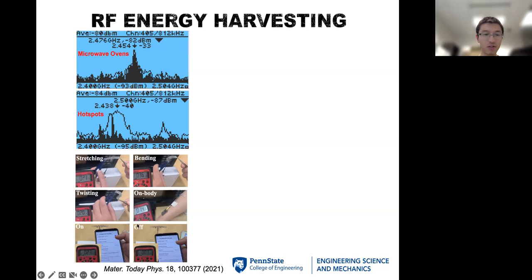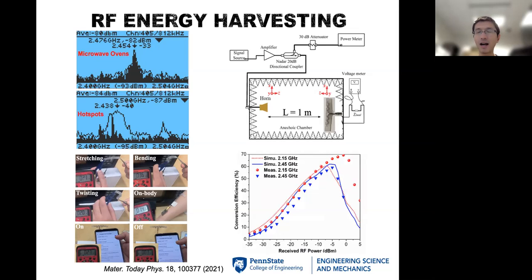And it can also harvest energy from Wi-Fi, the hotspot of the smartphone. And of course, in the ambient environment, the input power is probably 1 microwatt. I think it's negative 30 to negative 40 dBm if you do the conversion of the unit. And if we have much higher input power, like 0 dBm, which is milliwatts, you can have efficiency up to 70%. So in practice, if you are working with the device in an office space or in a building, you can have much higher efficiency to charge up your electronics and wearable devices in a very short period of time.